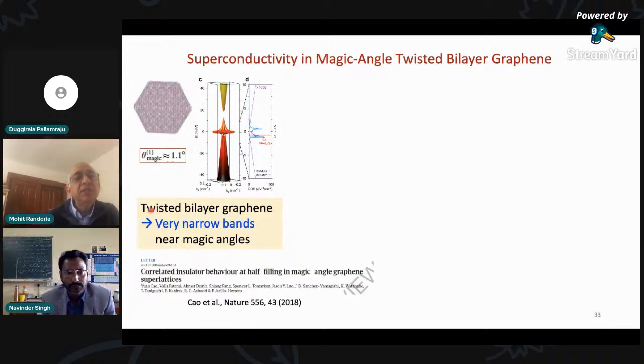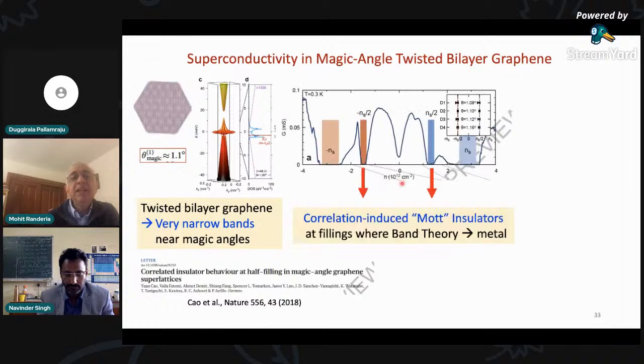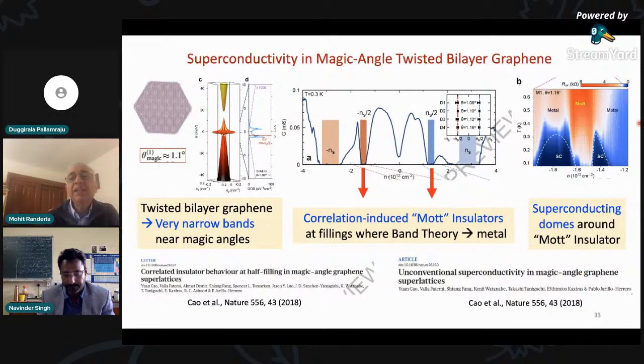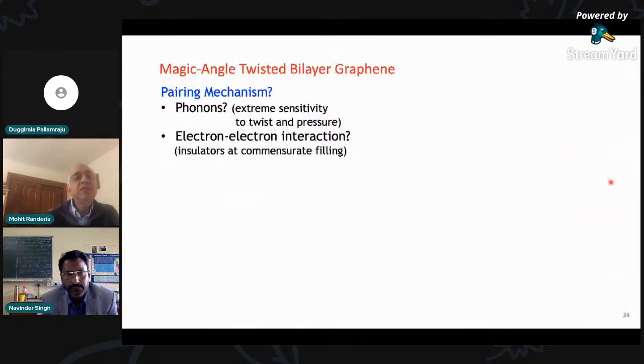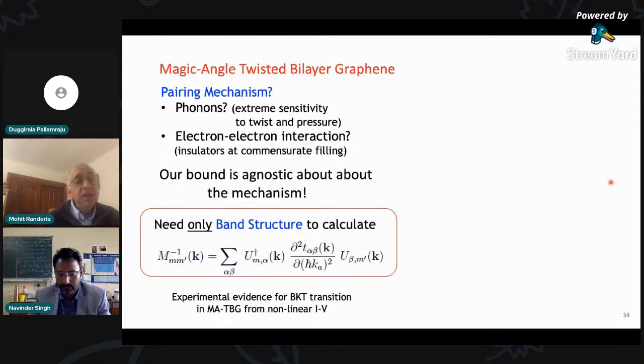So this, as I told you, is this very new development where you twist two layers of graphene with respect to each other. You get very, very narrow bands. And in this very narrow band system, you get correlation-induced insulators at doping levels where band theory would have told you that there's a metal. And around those insulators, you get domes of superconductivity. Again, very little is understood about this system. What the pairing mechanism is which gives rise to superconductivity, we don't know. Maybe it's phonons, maybe it's electron-electron interactions. Cases can be made for both of those arguments. Maybe it's both. But again, our bound doesn't care. We just need band structure.